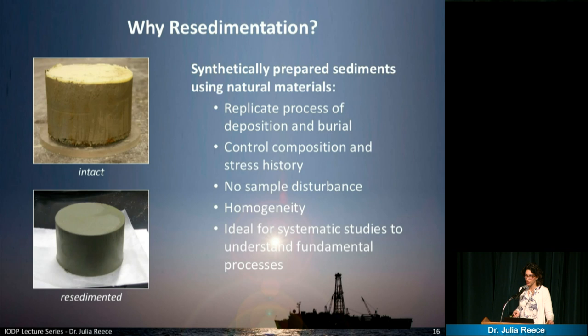And the advantage of this technique is that we end up with very little disturbance. The coring process itself causes a lot of disturbance in the sediment cores, but doing it in your lab, you can reduce these disturbances. And also, we can really control what we are putting in there. I often refer to this as baking. It's like making brownies. You use this much flour, this much water and sugar, you mix it together, and if you're happy with the result, you're happy, but if not, you might change a little bit. And if you only change one thing at a time, then you will actually know what really causes the improvement in your cake at the end. So that's really how we are doing it in the lab.